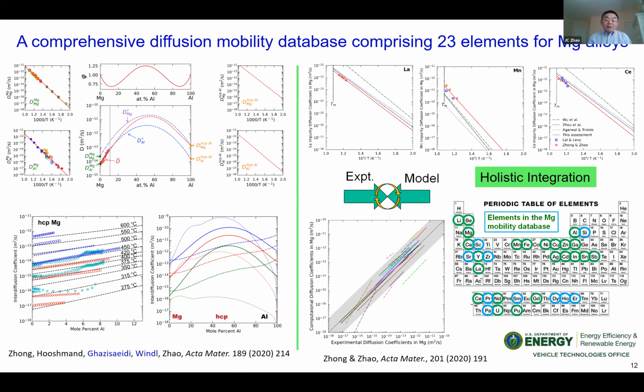From there, we established a very reliable and very comprehensive database. It has 23 elements, and this includes literature data. And then we also have 10 different elements where we provided computed data from groups like Ghazisaeidi's group, Dane Morgan and Dallas Trinkle's group. So you can see that if we plot all the experimental data versus the computed data, this line is the perfect agreement.